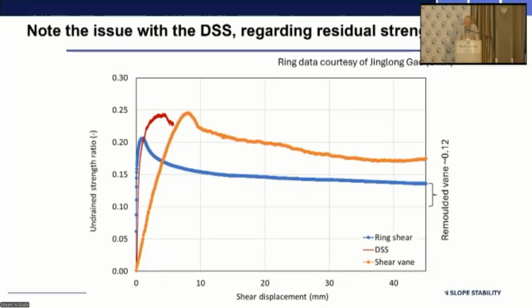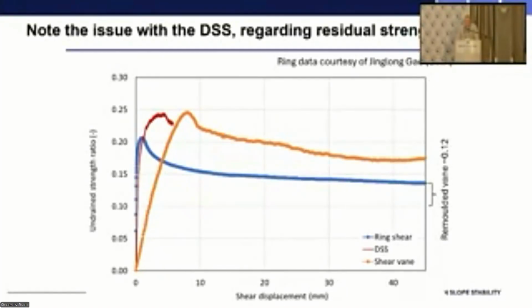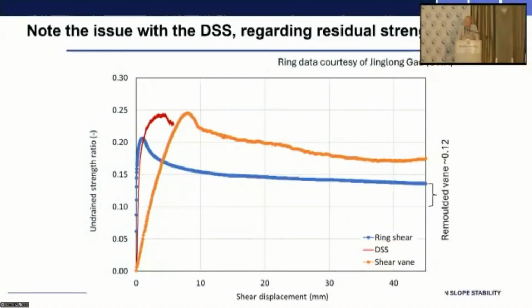And then you can see quite similar peak values, but in 2 cases you're able to monitor and actually get some handle on the large strain strength. And interestingly enough, for this material, those are at strength ratios way higher than we sometimes see in the literature for clay-like material, but 0.15, maybe 0.13 for large strain strengths. And incidentally, the remolded vane, where the vane was turned at high rates of rotation, we're giving about 0.12. So DSS is, I think, great for getting peak strengths, but it has to be used with caution for large strain strengths.